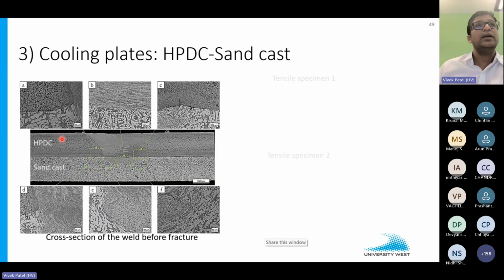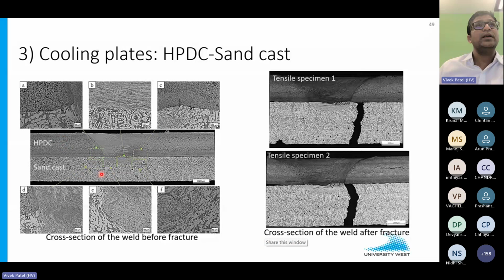Then here we checked the combination of die cast to sand cast, and you see that the weld nugget is intact. So the final failure is happening away from the HAZ and on the sand cast.